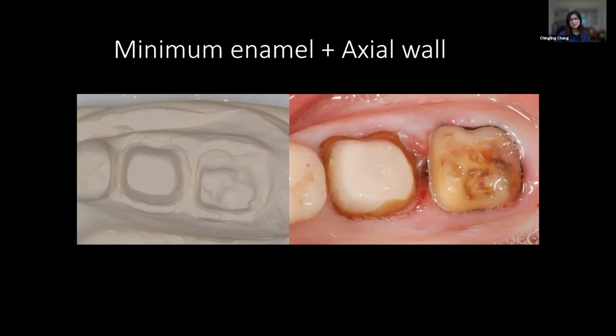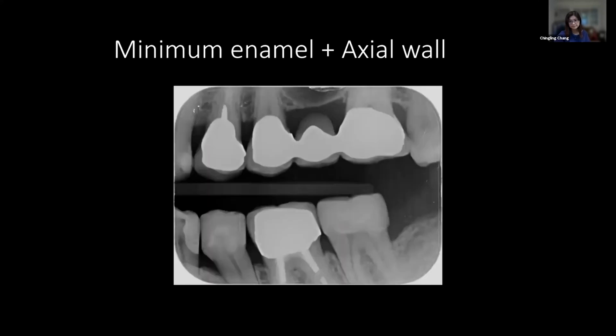But I still try to follow the principle. I try to just preserve the enamel if I can, very minimum enamel. And I try to gain the axial walls to get some mechanical retention for the restoration. And I did immediate dentin sealing to increase the bond strength for this case. And this is the cementation of the crown. You can see tooth number 37 has very minimum tooth structure remaining, but the crown has stayed in the mouth for more than 10 years.